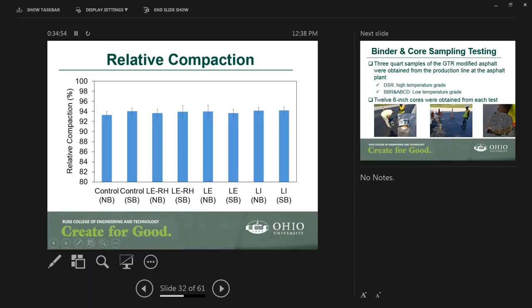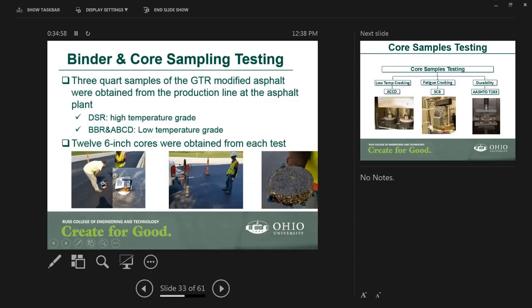What we have done there is measure the density, and at each spot where we measure the density, we also obtain cores. We had 6-inch cores. We also took samples of the binder at different stages through the production. So we got samples at the asphalt terminal, and then also at the production line, just to see if there is any separation happening during that process. We did DSR for the high temperature grade, and also BBR, bending beam rheometer, and the ABCD.